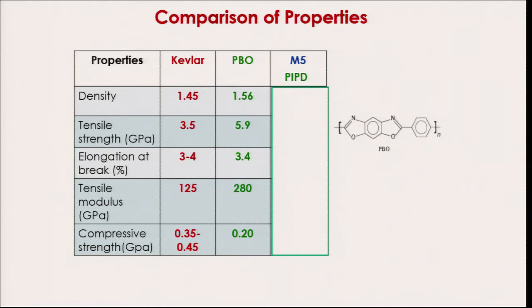In this case, the density is increased a little bit because the structure is more rigid, can pack better. The strength is 5.9 instead of 3.5, very high. Elongation remains almost the same. The modulus has become more than double. So, can you see how the structure is affecting the properties?